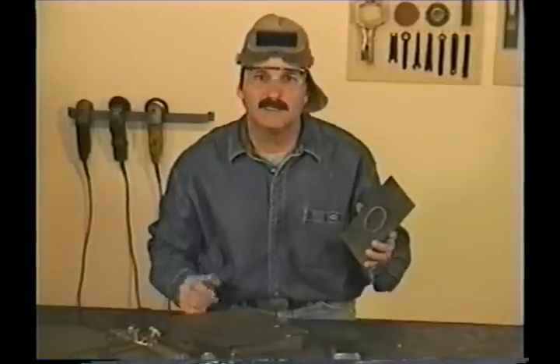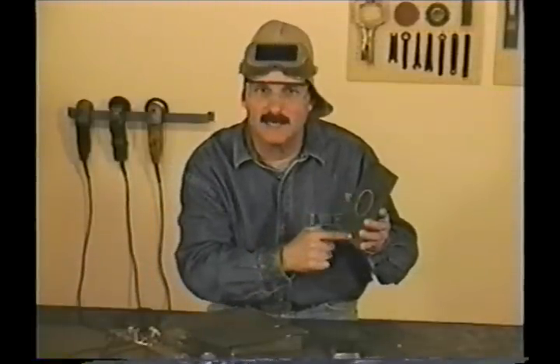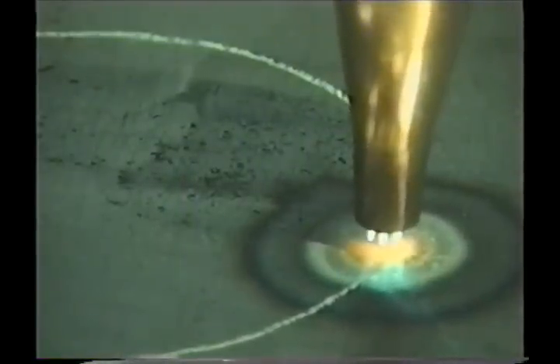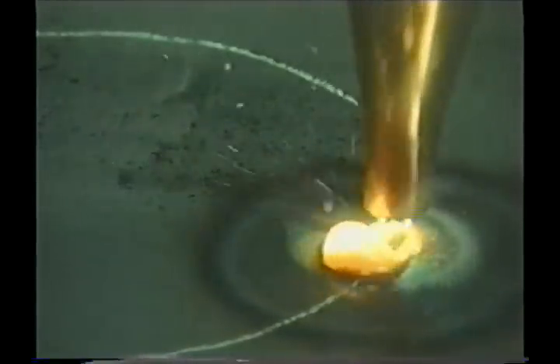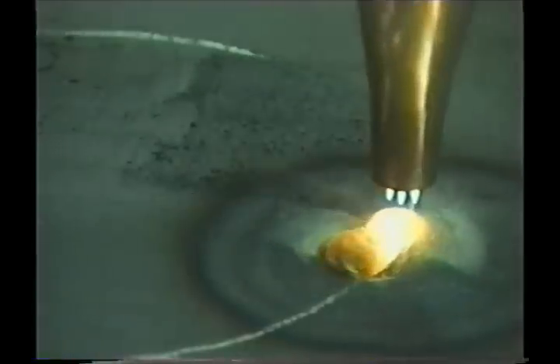Occasionally, you'll get in the position where you need to save both the inside and outside pieces. So you'll have to start right on the cut line. Here again, preheat a little hotter, ease on the cutting jet, and move the tip. When you're all the way through, cut back just a little, then go on to make the cut. You're able to cut back through the slag because everything is still hot from preheating for the start. By cutting back a little, you'll have a relatively clean place to finish. If you leave that mess, when you come all the way around to finish and the cutting jet hits the cold slag, it'll probably gouge into the sides of the kerf.